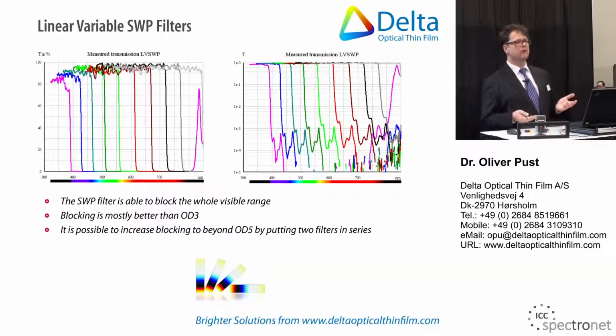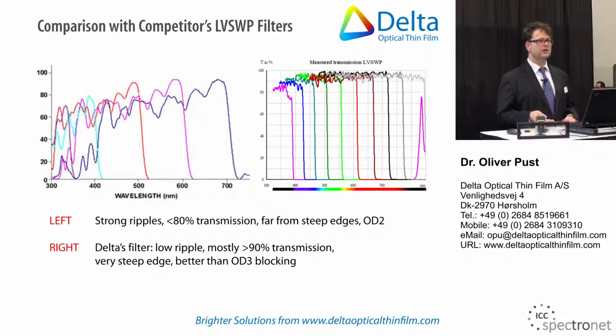And here the comparison with older technology is even more striking. So you really have to look closely to recognize the short wave pass filter. The transmission drops rapidly away from the edge. It's not steep at all, and then again severe leakage effects in the rejection band.